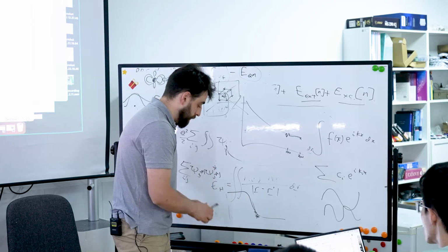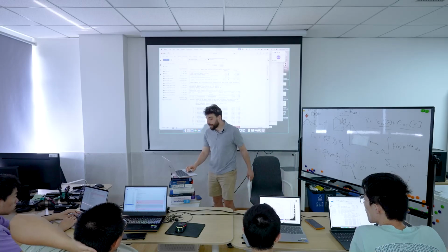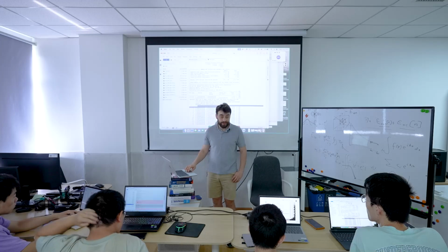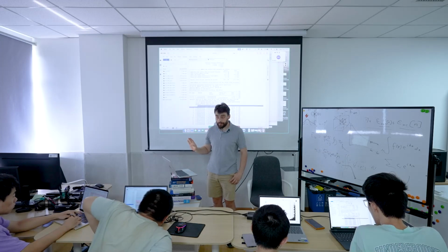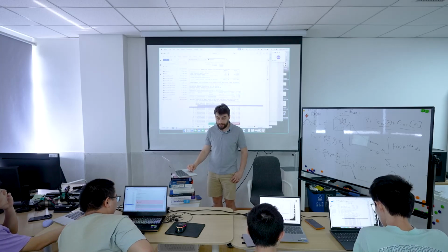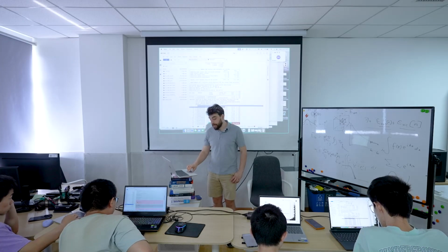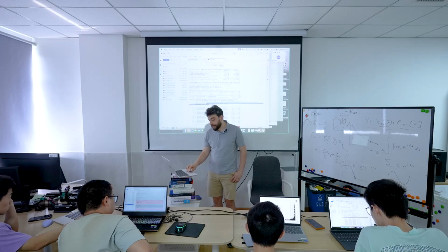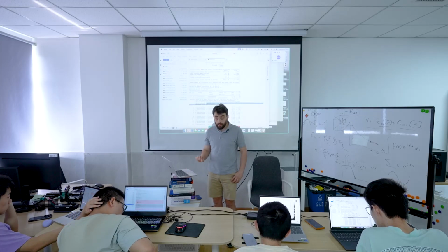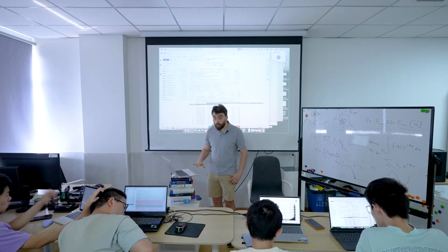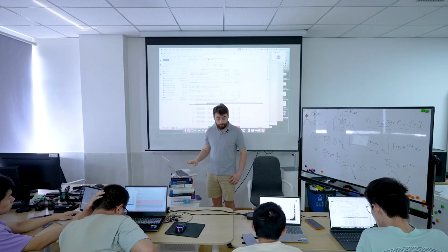However, in the next iteration, we can see that it did not complain about empty bands. So this was only a problem for the first iteration, and then it went away, so we can ignore it. If it complains about extra bands, then we would need to do something about it. We would need to add a parameter like nbands extra in the input file. Because this warning has gone away after the first iteration, we can ignore it, and we don't need to worry about it.